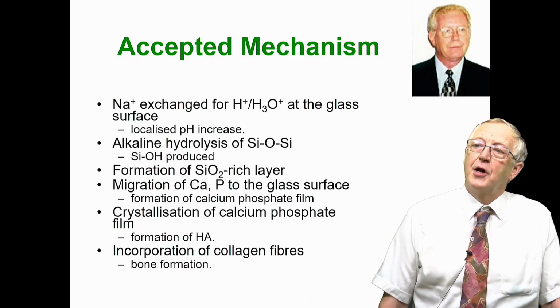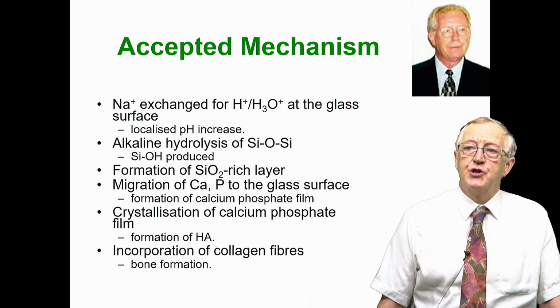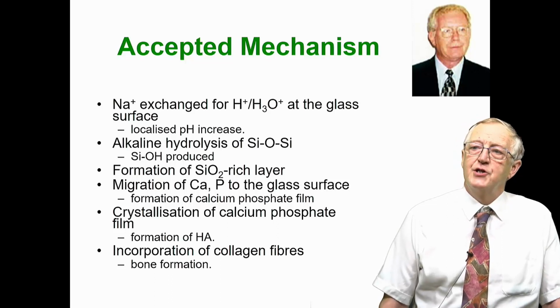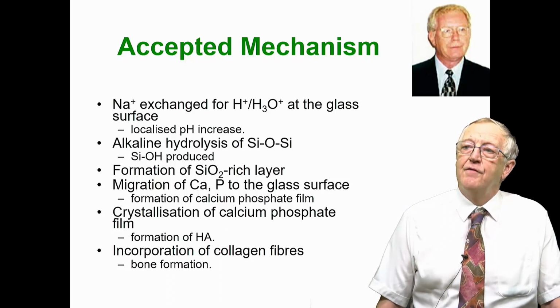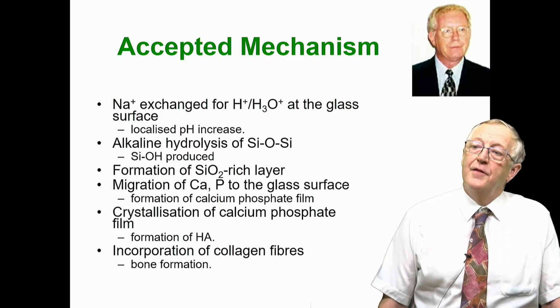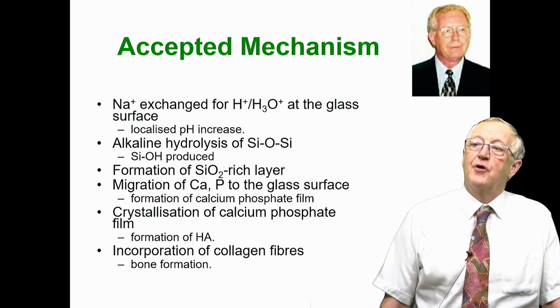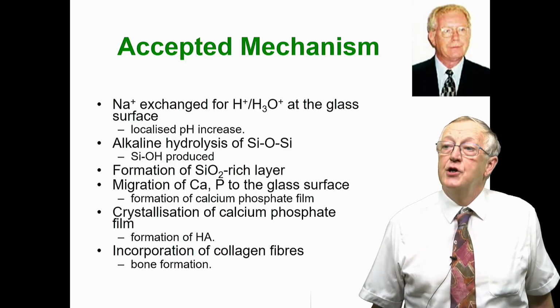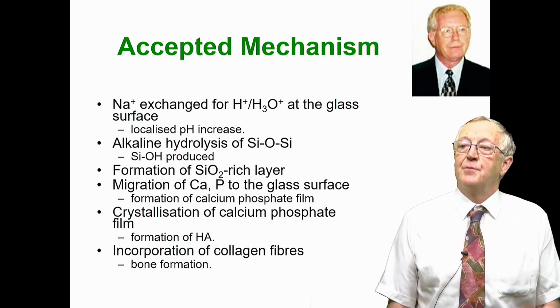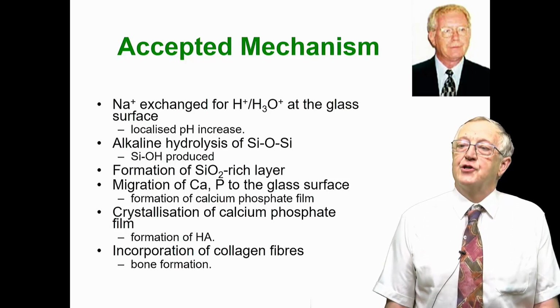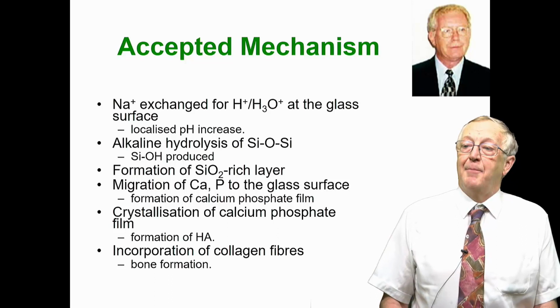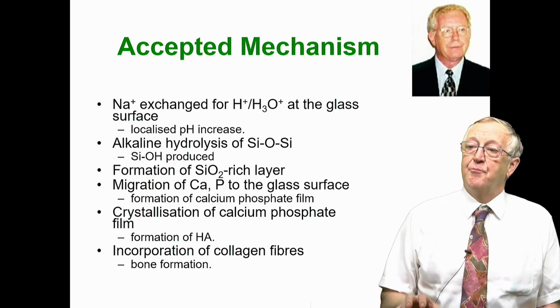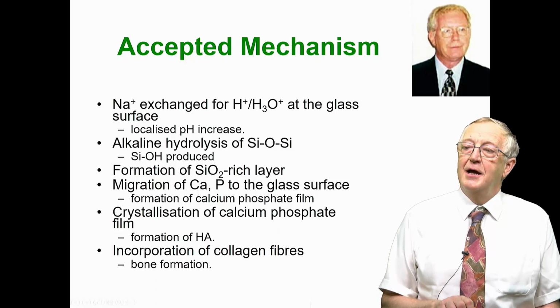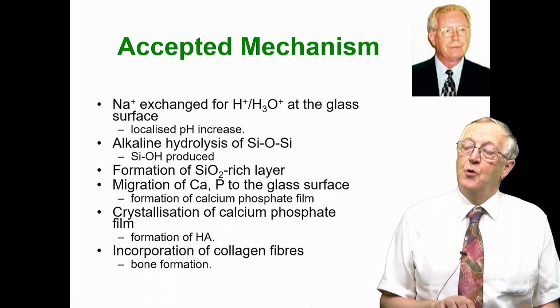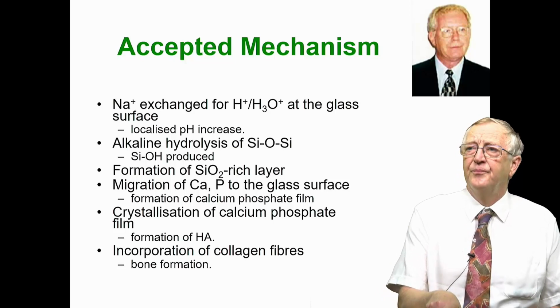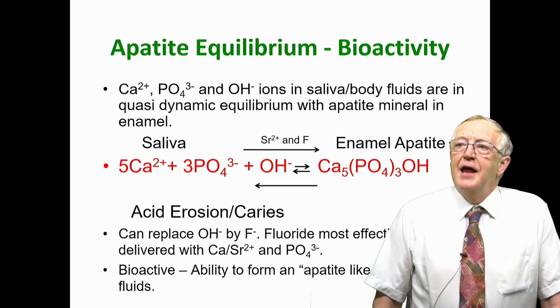This is then followed by alkaline hydrolysis of the silicon-oxygen bonds of the glass network, the formation of what we term silanols, and then the formation of a silica-rich layer. And this is then followed by migration of calcium and phosphate to the glass surface to form a calcium phosphate film, and this crystallizes to form the hydroxyapatite, or HA. And in the case of bone, this HA becomes incorporated with collagen fibers, which stimulates bone formation. In the mouth,